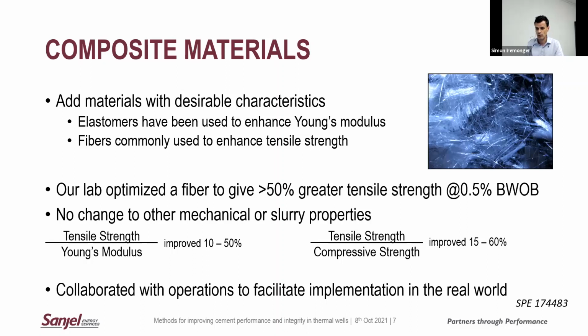I won't go through all the slurry properties, but essentially we saw no difference in the slurry properties, no issues there, and no change to the other mechanical properties at all. So we're not sacrificing Young's modulus to do that. We saw good improvements in the ratios of tensile to Young's modulus and tensile to compressive strength. And one important thing when you're doing this work is to think of how this is actually applied in the field.